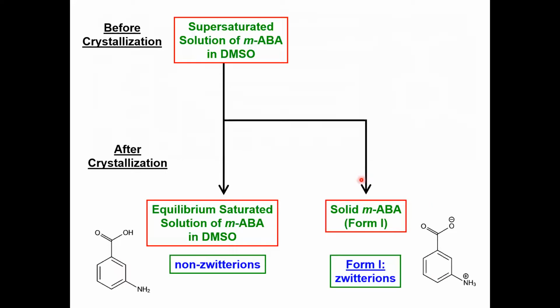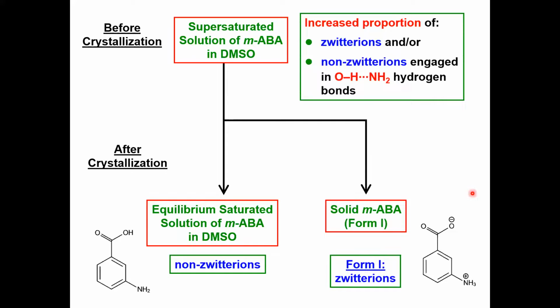So what we know is at the end of the experiment, we get solid m-ABA form 1, and this is a zwitterionic solid form. We know that in the equilibrium saturated solution, in the liquid phase, the molecules are non-zwitterionic. And if we rationalize all of these changes in chemical shifts, looking back in time in the liquid phase, what we deduce is that the pre-nucleation supersaturated solution relative to the final equilibrium solution has an increased proportion of zwitterions or non-zwitterions engaged in OH-N hydrogen bonding.